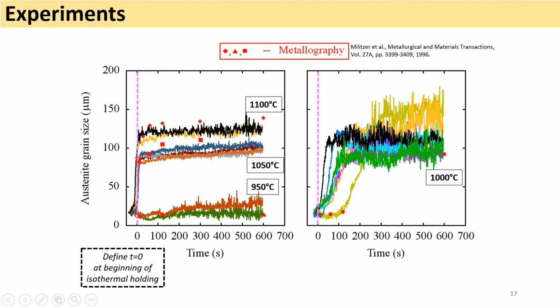What was quite interesting in this alloy is at 1000 degrees, you see, we have done many tests, and every time that we would do a test, the grain growth curve would always be very different. You can see that the sharp rise in grain size occurs either very shortly after the onset of isothermal holding, or only about 100 to 150 seconds after the onset of isothermal holding. So this is a typical sign of abnormal grain growth occurring inside the sample.